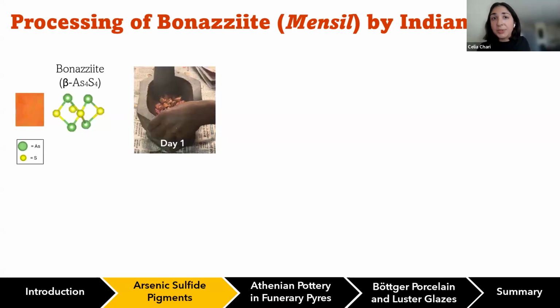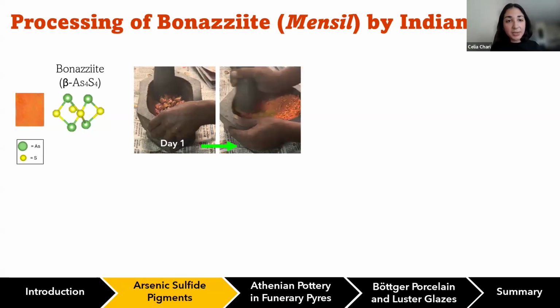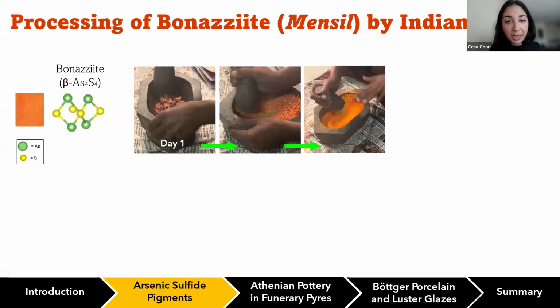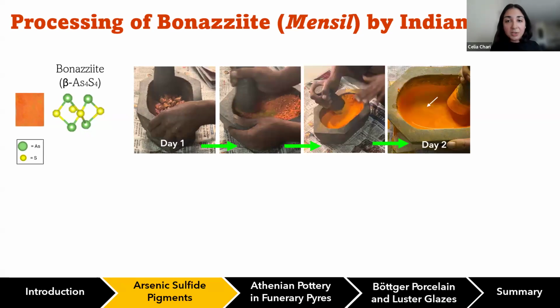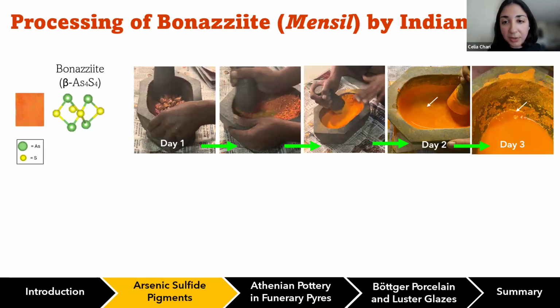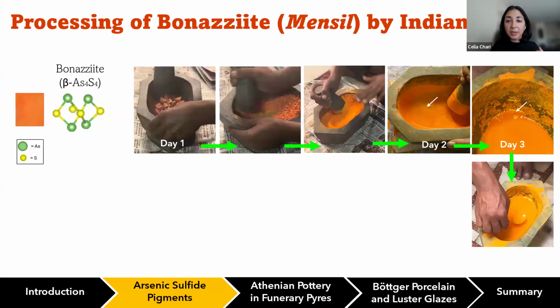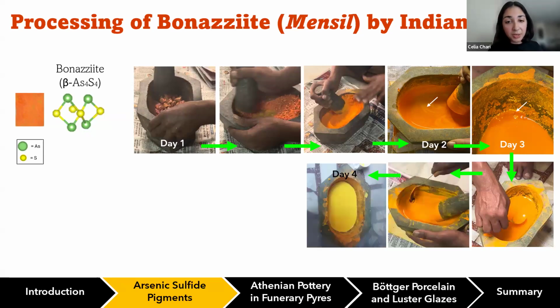So to understand why it was that he didn't notice that, we followed the way that he processed bonazziite over an 8-day long process. So starting off, as I mentioned before, he takes these chunks of bonazziite, he grinds them down, and with the addition of water and further grinding, you can start to see little yellow streaks and yellow globules start to appear. He actually removes them and continues grinding the pigment over and over, adding the binder directly to it. So he's basically creating the paint during this process.